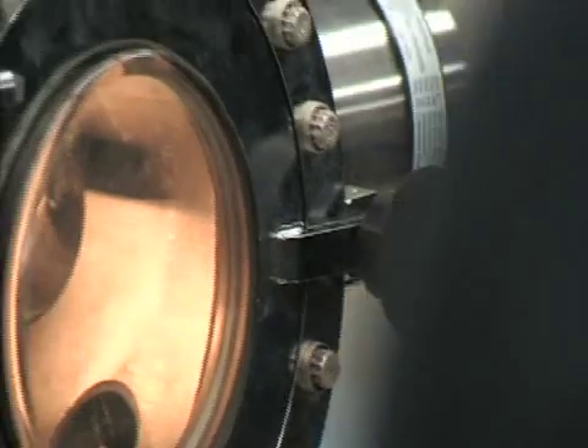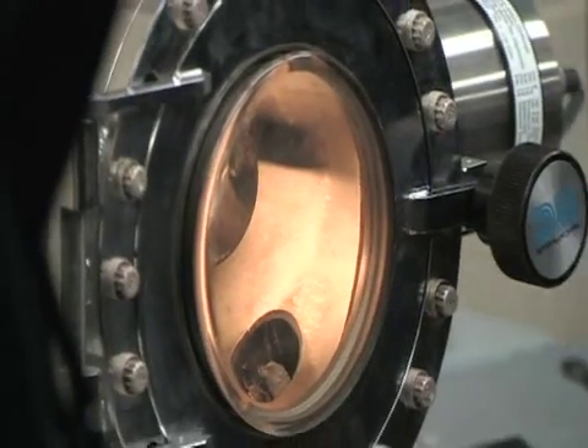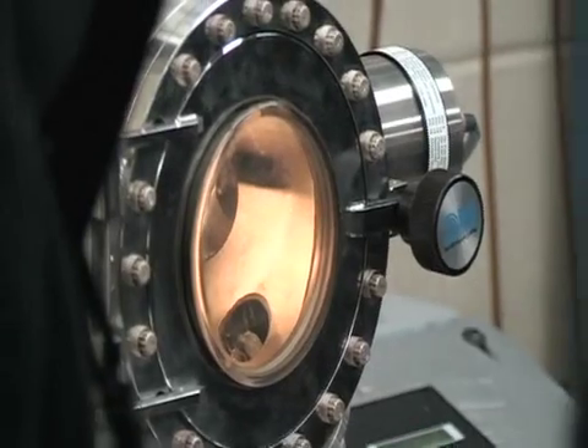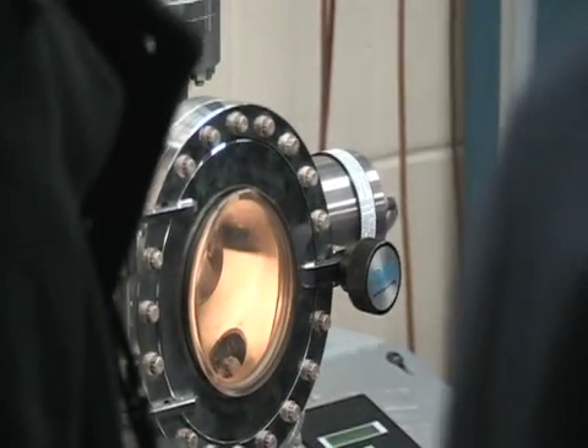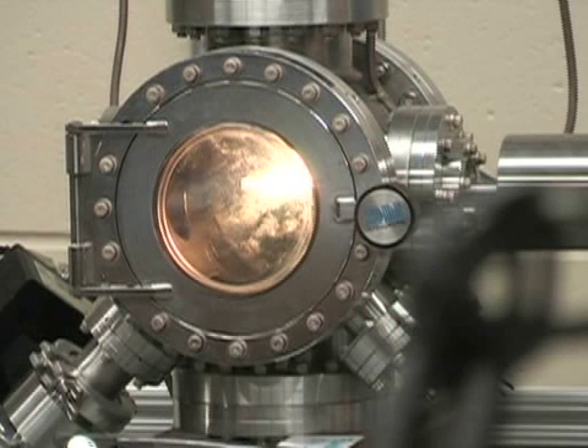One of the great things that we found in micro end milling is the low friction and the low adhesion of materials to diamond. Why? Diamond bonds are very strong. Unless you get a dangling bond out there, they don't want to attach to other things. That's why you get low friction and low adhesion. And this has great benefit as we shrink down. We get more surface area for the volume we're trying to cut, and so it helps a lot.